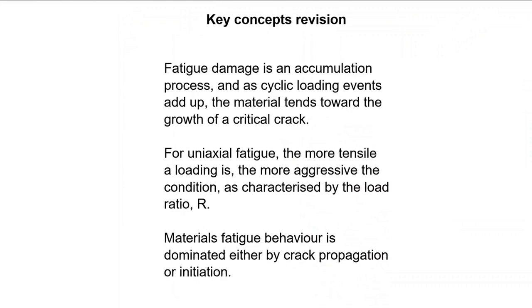So, we have studied a degradation mechanism that involves the gradual accumulation of damage to a material due to cyclic loading, occurring well below the yield strength of material. We have seen how different types of material react to this type of damage through different propagation rates of fatigue cracks. Some are initiation dominated and others are propagation dominated. We have reviewed how fatigue behavior is characterized by SN curves, and that the most aggressive conditions for any material is when the load ratio, or the ratio between the minimum and maximum stress, is greater than -1. This is because compression does not serve to open cracks, only tensile stresses do.